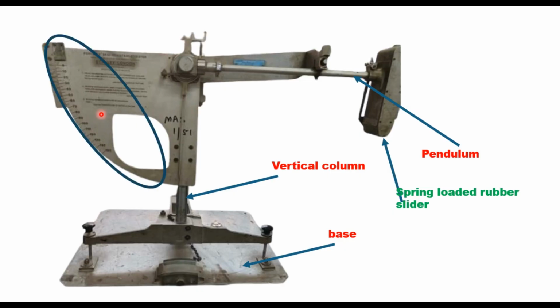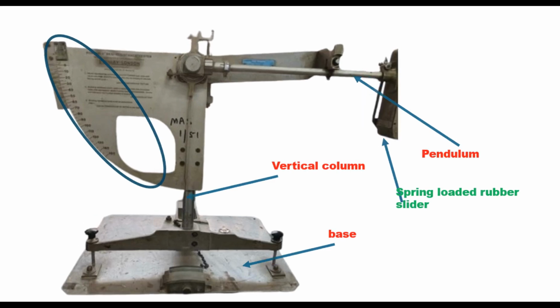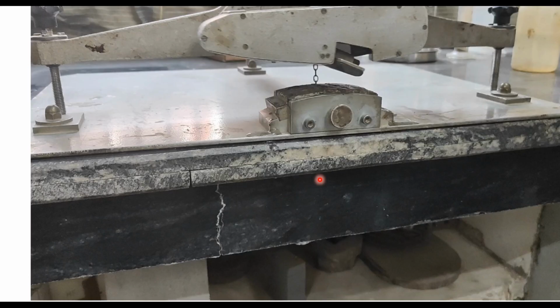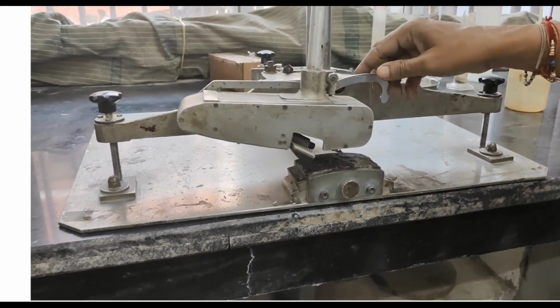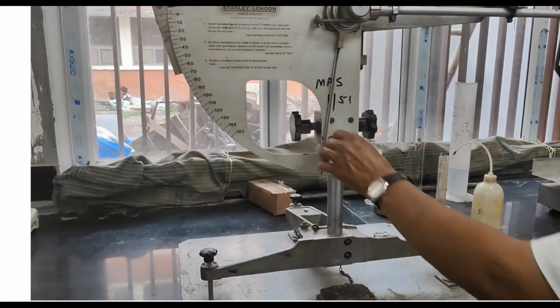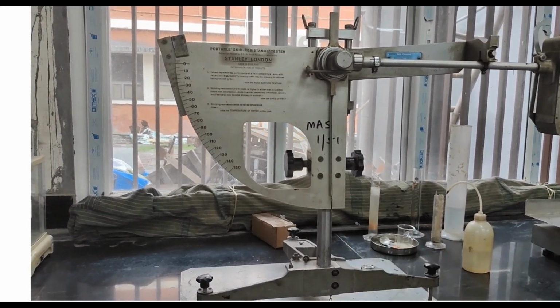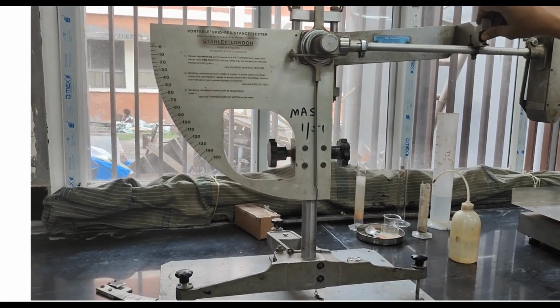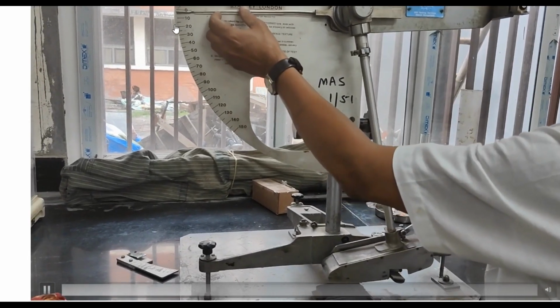Here is the plate with graduated scale along the arc indicating the skid number or PSV, and these are from 0 to 150 here. This dead pointer is fixed at the hinge of the pendulum to indicate the position or height of the pendulum achieved during friction test. Rest the friction tester on a firm level. This pendulum should be in the air without touching the specimen, and you release it from the horizontal position. In this position, this pendulum should go up to a zero position here. If it does not go up to zero position, then you slightly loosen it from the hinge here.